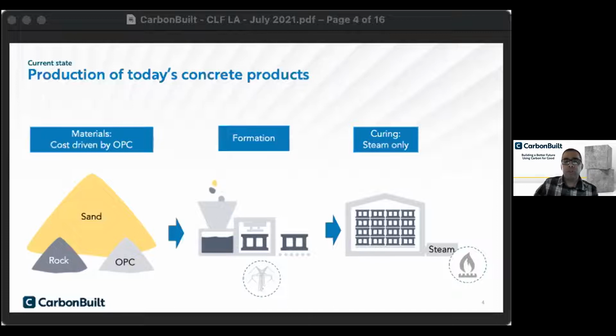And then those products are moved into curing chambers where the hydration of Portland cement, which is the core set of reactions that's taking place, is accelerated through high temperature and humidity. In some cases, producers have started to add fly ash or slag to their mix. Historically it was done to reduce cost, but certainly today it also has the impact of reducing carbon footprint. In this case, the calcium hydroxide that is evolved in the hydration of Portland cement is further reacted with fly ash, for example, to make more of the CSH glue that is really the core piece of the binder in concrete.